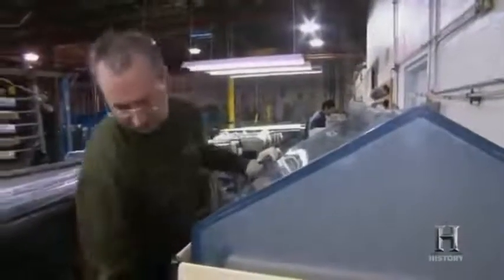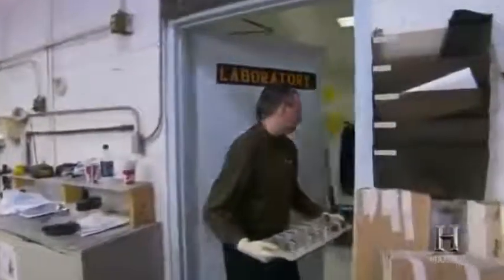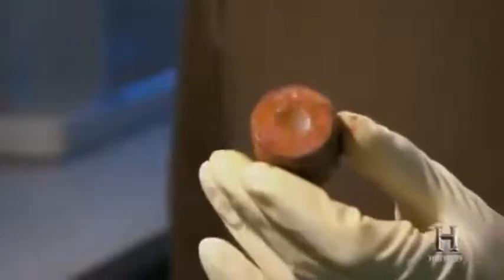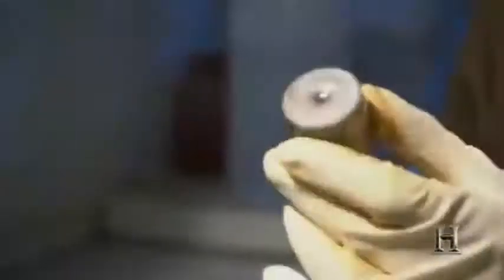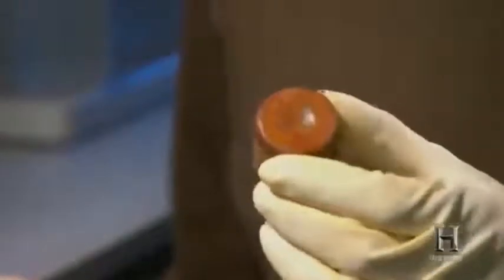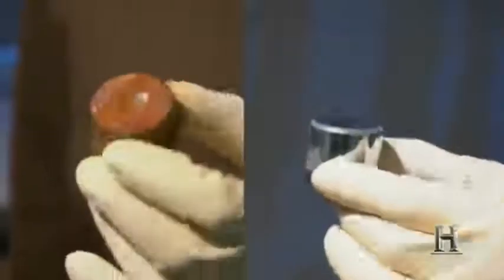To test this resistance, Arlington Plating Company technicians turned to a salt spray chamber. Placing parts in the chamber for just 8 hours simulates more than 2 years of real-life use. This is an unplated part, just raw steel part. As you can see, it rusted, the iron rusted, forming an iron oxide. This is a nickel-plated part, slight rusting, a little bit of yellow. And then we have the chrome-plated parts. As you can see, virtually flawless finish, no visible rusting at all. Chrome actually does rust like all other metals, but at a much slower rate. And unlike the eyesore of iron oxide, chrome oxide is clear.